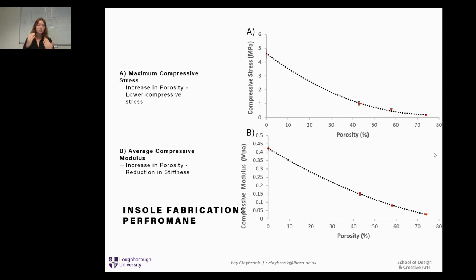So if we link this back to the study that was done by Holmes et al., it was found that the gyroid TPMS structure that they tested was comparable to the split P that was used in this study. The gyroid structure had approximately 0.125 MPa at 10% strain, and comparatively, the split P in this study was found to have 0.2 to 0.3 MPa, which is twice the compressive stress loading capacity.